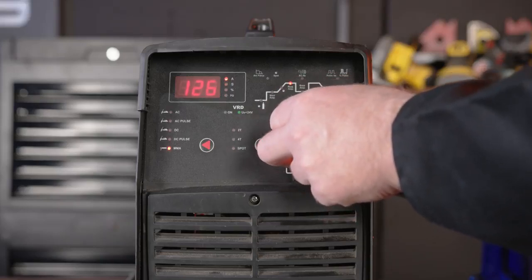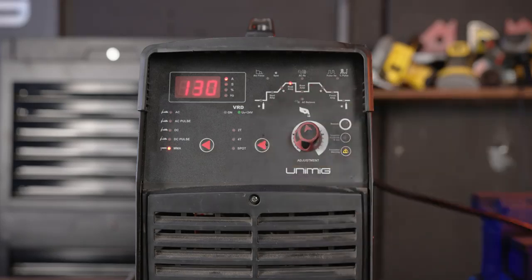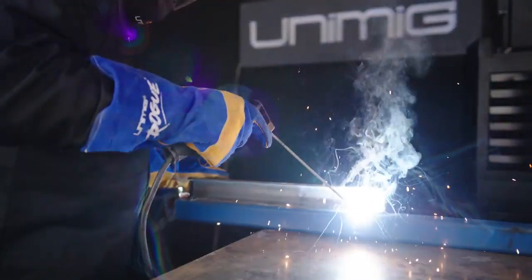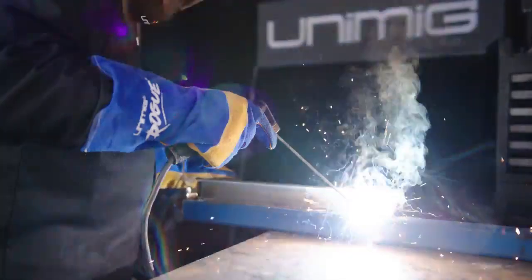Welding on DC positive gives a more stable, high penetrating arc, while AC gives less penetration and eliminates arc blow. The way to know if your amps are wrong comes down to a bit of experience. For example, if it's hard to start an electrode, it sticks, or the weld metal is sitting on top of the parent metal without burning in, then you know that the amps are too low. On the other hand, if the arc is gouging without filling, leaving undercut and burning really hot, then you know that your amps are too high.